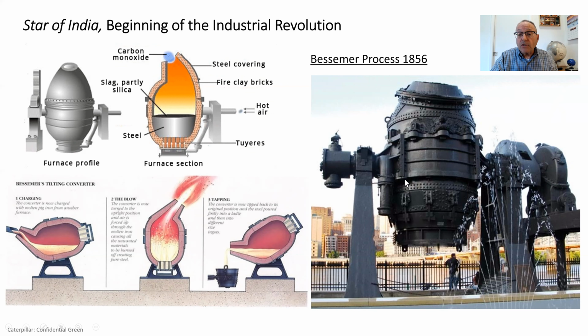And you can see here the size of the vessel relative to a person standing next to it. Now this process, the Bessemer process, was able to produce low carbon steel in minutes, whereas the open hearth process took hours, on the order of 8 or 9 hours. So this meant a lot. What happens now is we have two competing events that occurred. One is we have an abundance of cast iron that's made by the blast furnaces. And now we have a process where we can reduce the carbon in that cast iron very low and produce a forgeable steel, or low carbon iron, that we could easily forge and make into products.